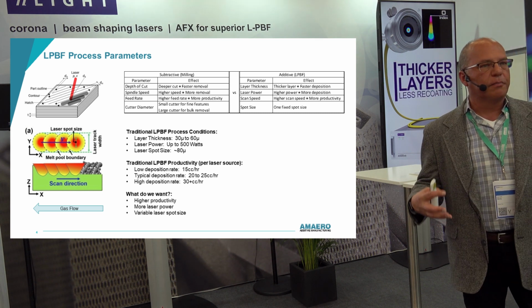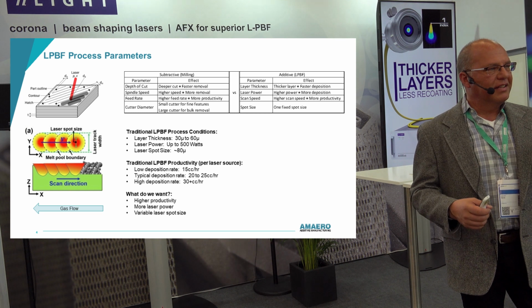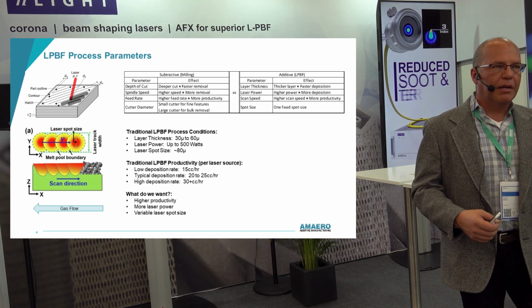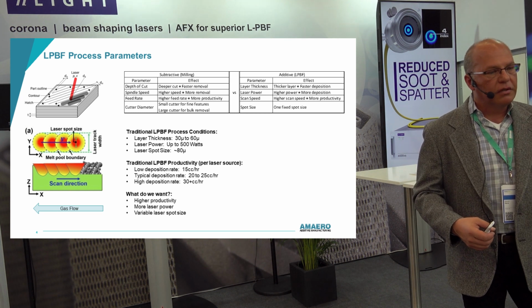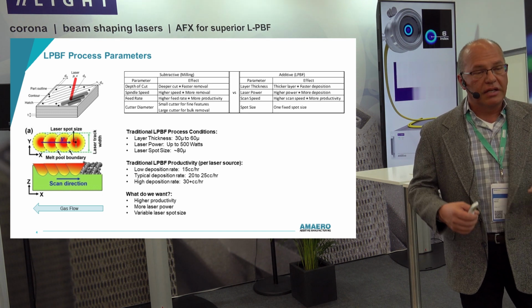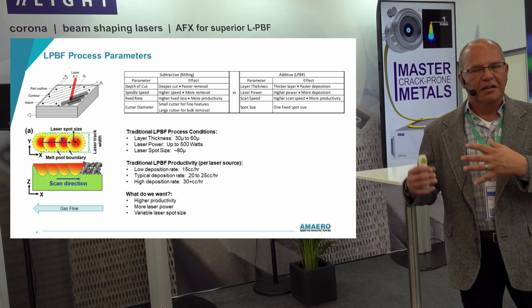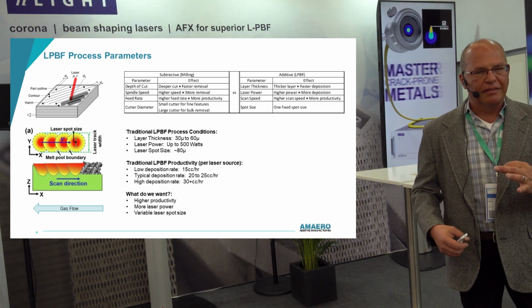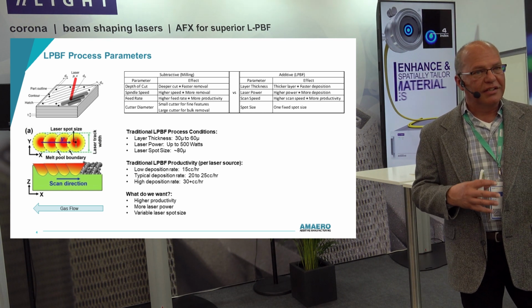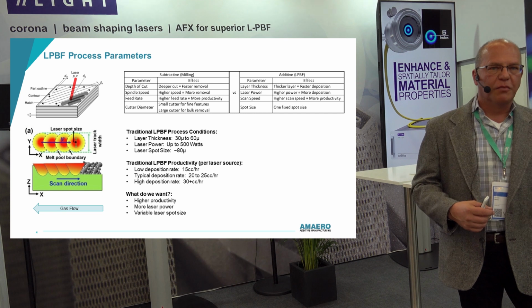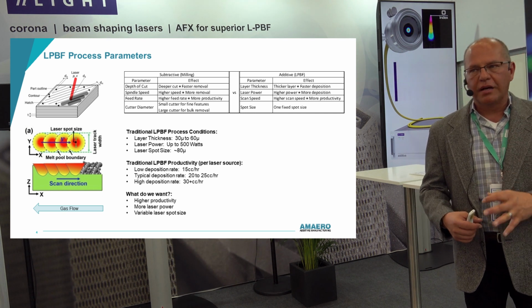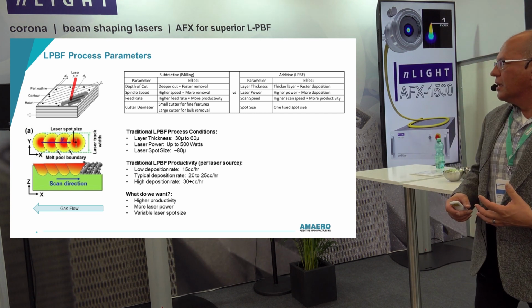Where the analogy falls apart is that in milling, we can put in a small diameter mill and mill a very fine feature, change to a large diameter mill, and take away a lot of material. On the laser side, we only have one spot. We can't change it historically, but that's what we really want to do: small spot for fine features, large spot for massive deposition.